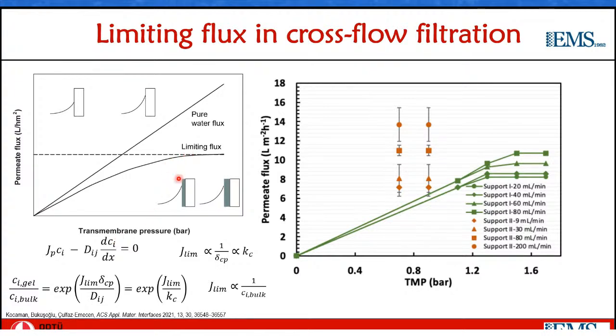After the limiting flux is reached, the two ends of the boundary layer are now at fixed concentrations of the bulk concentration and the gel concentration, and hence these are related to the limiting flux as follows: through the diffusion coefficient of the filtered material and through the thickness of the boundary layer, or as the ratio of the diffusion coefficient to the boundary layer thickness, which is the mass transfer coefficient. So what we expect to see in the cross-flow filtration of a colloid is that the limiting flux should be inversely proportional to the boundary layer thickness, or directly proportional to the mass transfer coefficient, meaning the higher the cross-flow velocity, the higher the limiting flux.